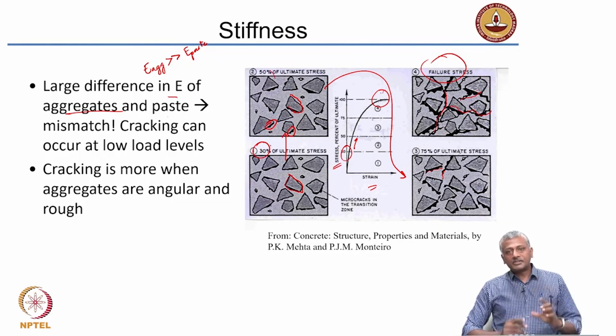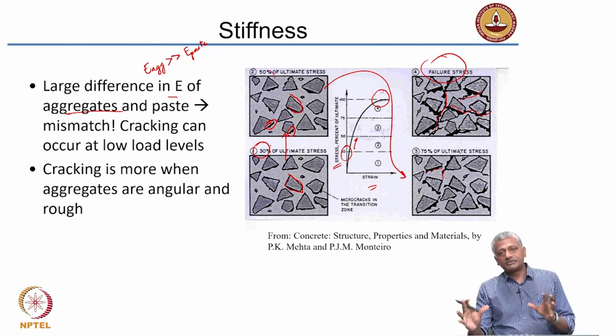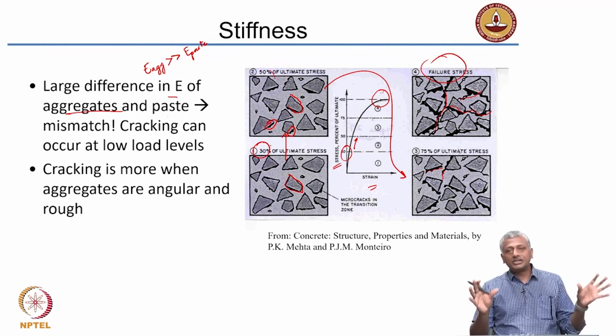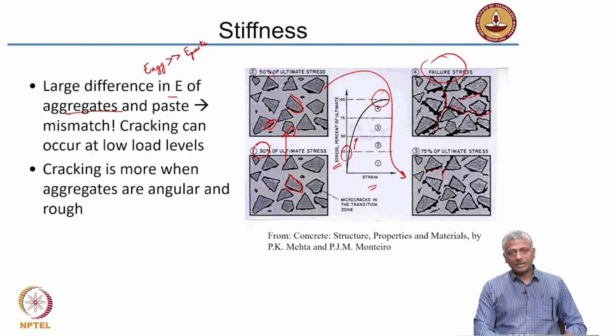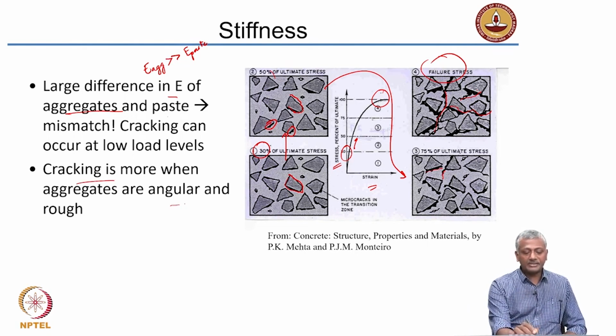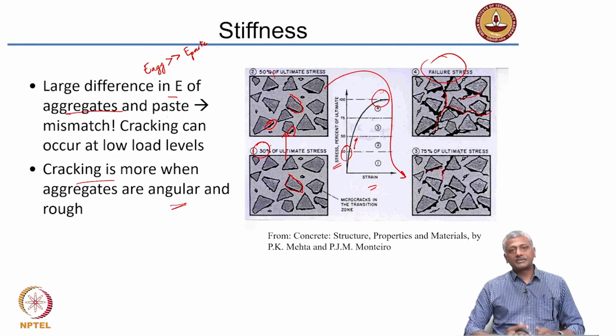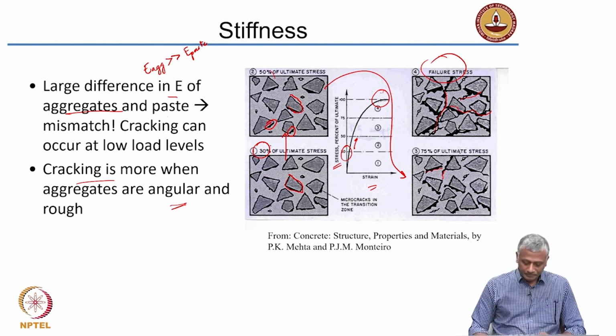So, the more mismatch between the modulus of the paste and the aggregate, the greater the initial cracking that you get. The lesser the mismatch, the lesser will be the initial cracking. So, this will affect the overall load carrying capacity of the concrete itself. And cracking is generally more when the aggregates are angular and rough, because then any movement of the paste also will be restricted by the bond between the paste and the aggregate. So, when the aggregates are angular and rough, the cracking is going to be more as compared to rounded aggregate.